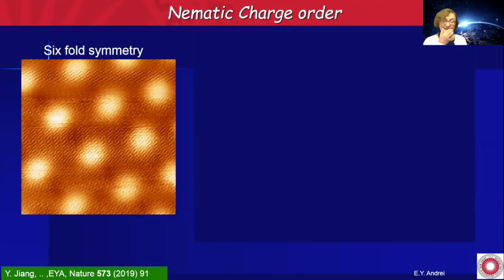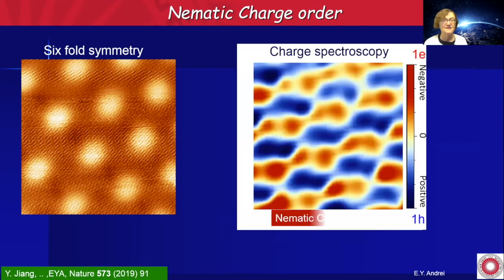And what we did next is we were asking, is there nematic order here or not? So what we did, we devised a way to actually measure the charge distribution inside the sample. I don't have time to go into how this was done, but we could measure the charge in the system. So you start out with topography. You have a clear, beautiful six-fold symmetry here. These are the AA regions. And now we measure the charge spectroscopy in this region. This is exactly the same region of the sample. And you see that the charge has broken up into stripes. We have nematic or stripe order.